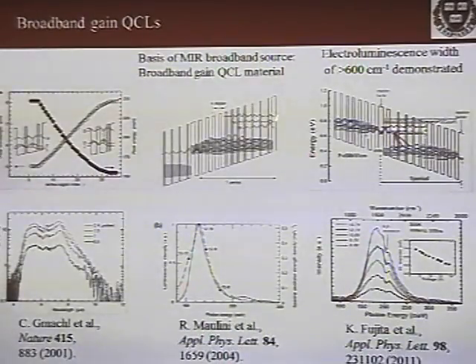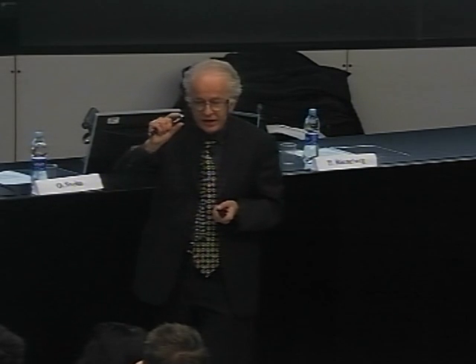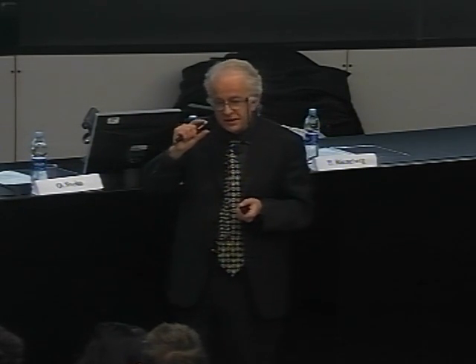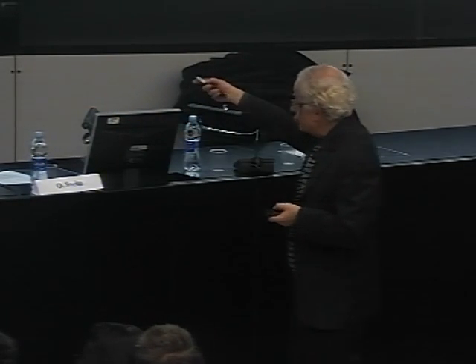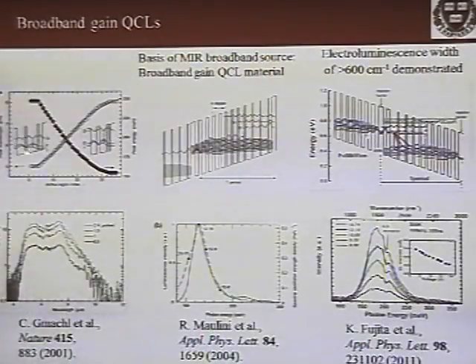So then you have to go back to your quantum wells, you see. And in the structure you showed before, I have many stages. All the stages were the same. So you can expect, if all the stages are the same, that this device will have a narrow gain spectrum. But if you now want to make it broad, the idea conceptually, qualitatively is simple. I want to put some stages which are certain at one wavelength, another at another wavelength, and so forth. And this is what we demonstrated in this paper in Nature, where by changing the thickness of the layers, as we move down the structure in groups of stages, we could have quite a broad gain spectrum. We were able, in fact, to laser simultaneously between about 5 micron and 8 micron